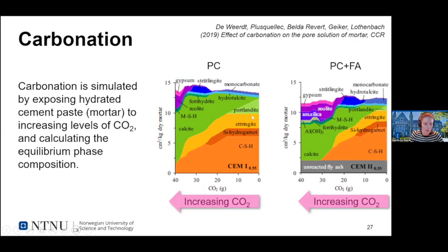In order to have all Portlandite reacted with CO2, we need a certain level of CO2. When we look at the fly ash cement, the pozzolanic reaction of the fly ash has consumed quite a bit of this Portlandite, so we need much lower levels of CO2 to consume all of it. Another thing we can see based on this phase assemblage is that when Portlandite reacts to calcite, we get a nice volume increase. The calcite has a larger volume than the original Portlandite. This has a clear effect for the Portland cement, whereas for the fly ash cement, there's only a slight increase. This indicates that with Portland cement, we can have a pore tightening effect of carbonation, and that effect is not that clear for a composite cement.